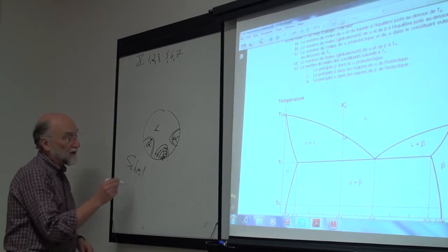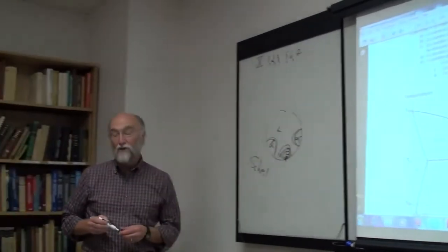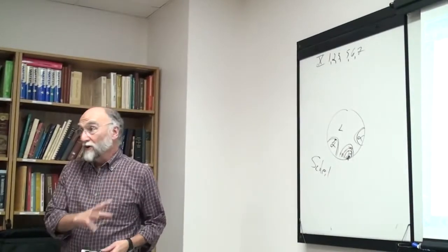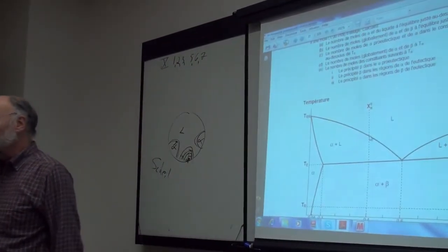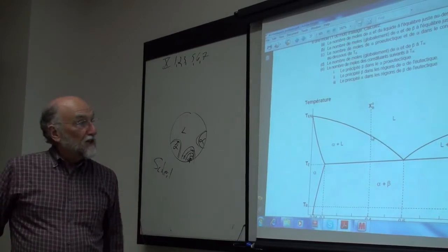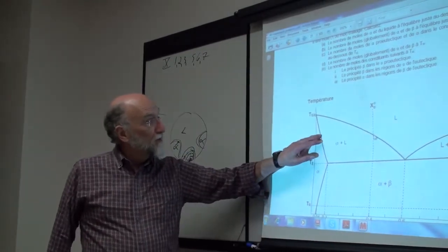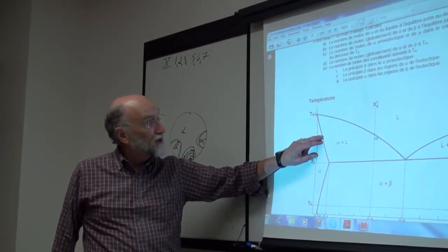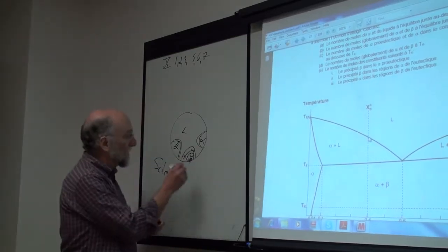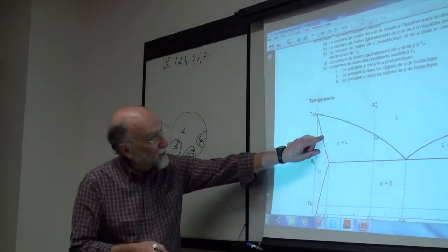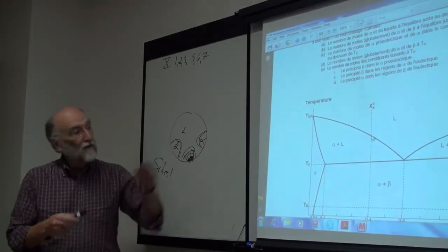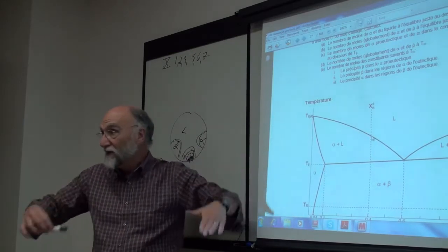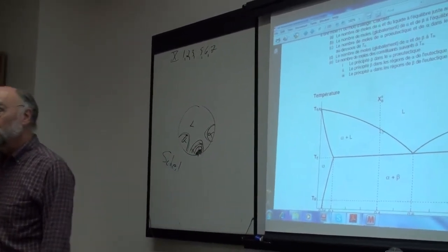If you're doing Scheil cooling, then the lever rule isn't going to apply. But you can still do a mass balance, step by step, by an iterative procedure. This is how FactSage works. On the Scheil cooling, FactSage will assume that a very small amount precipitates at this temperature, removes that from the equilibrium, then takes another little bit that precipitates 5 degrees below and calculates the composition of the second layer, removes that from the calculation, moves down, and you can do the Scheil cooling that way.